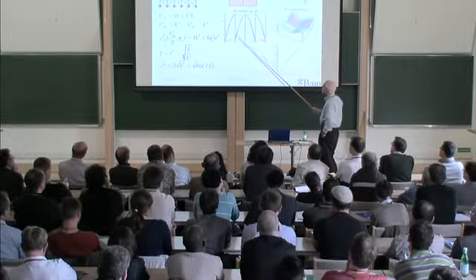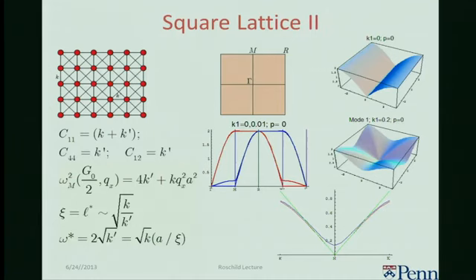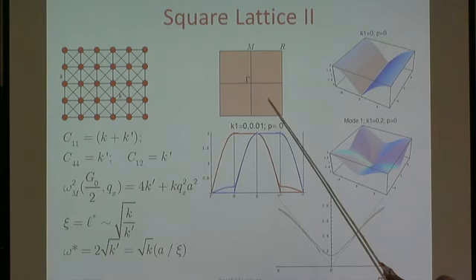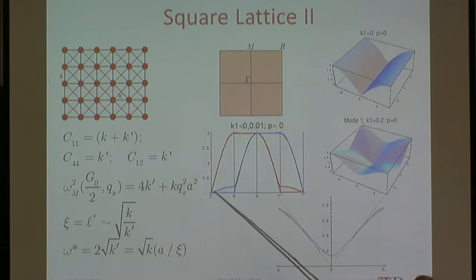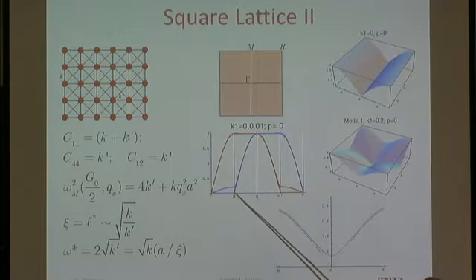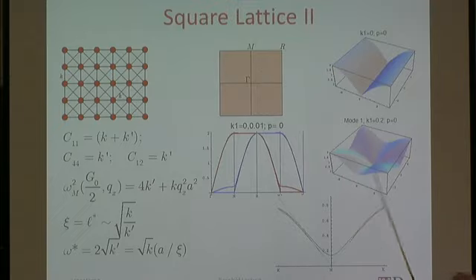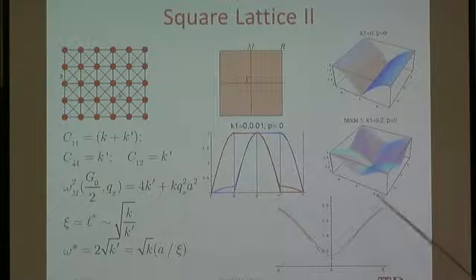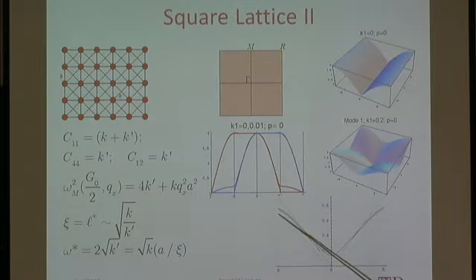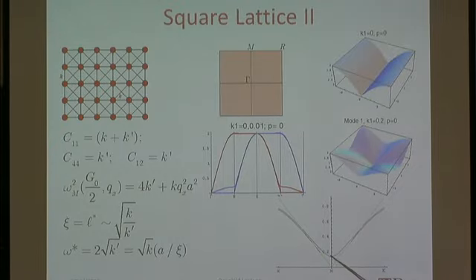When I add the next nearest neighbor forces, we get a gap in the spectrum at m. So here, this is going from gamma to m, which is from here to here. I have basically a phonon structure, and there's a gap everywhere except at 0. And if I plot from m to r, that's what this is. In the absence of next nearest neighbors, I have basically this V-shaped spectrum with a linear dispersion going from here to here. And I turn on the next nearest neighbors, and I get a gap.